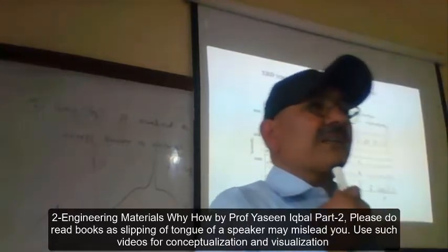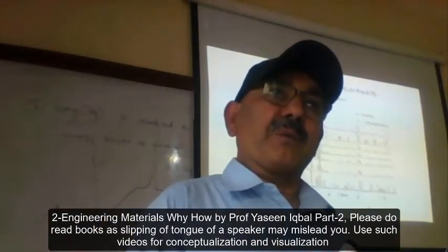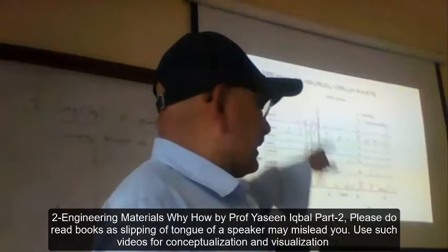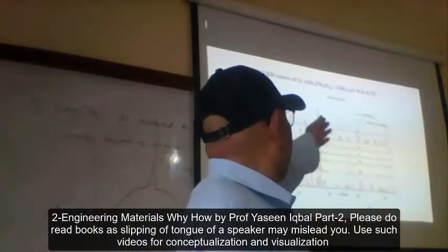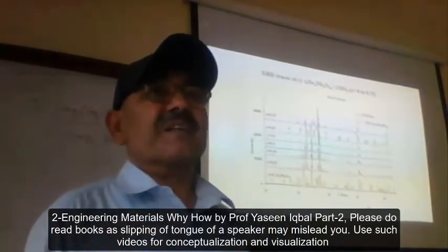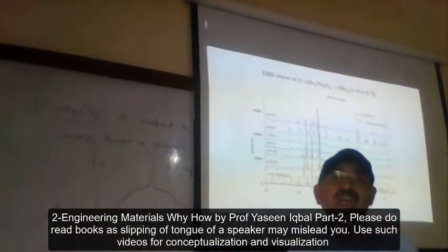tungsten bronze structure, TTB. Tungsten bronze structure is a known structure within crystallography. So the one that is Sr2Nb2O7 is one atomic structure, and the second phase that forms because of titanium addition, its composition was this: Sr3Nb4TiO15, and it is a tungsten bronze type structure.